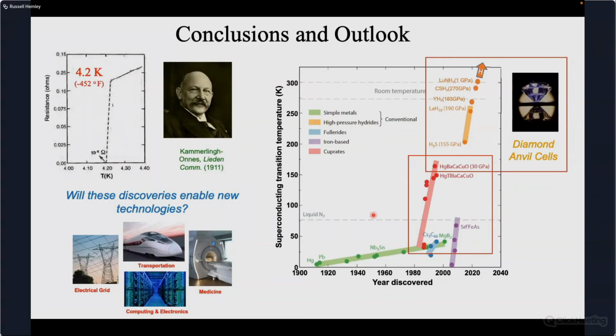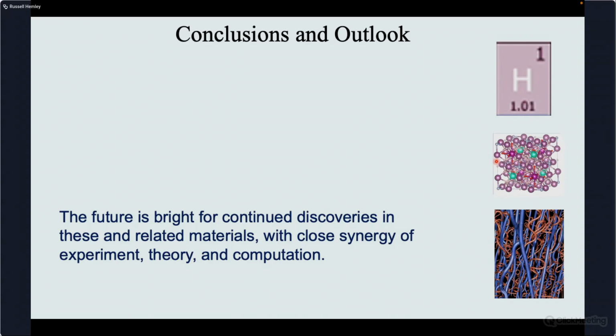Our plot of superconducting TC versus time: the conventional superconductors, the cuprates, the pnictides, and the iron-based, and then the regime now of the hydrides, which is in the vicinity and even possibly above room temperature. So the future is bright for continued discoveries in these and related materials. Again, as a result of the close synergy of experiment and theory and computation and simulation, we still want to look for new phenomena, for example, in pure hydrogen, look for new materials, and the focus is really on complex chemistry to realize some of these phenomena.